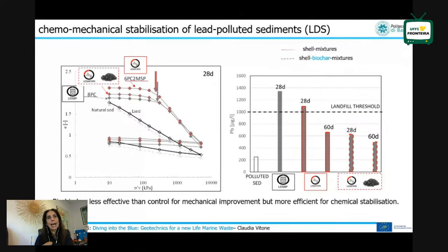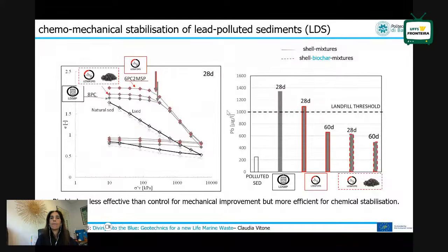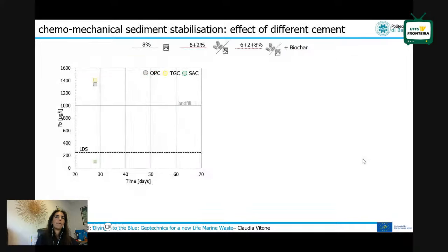On the chemical side, the leaching tests are very interesting here, because you can see that compared after 28 days with the control mixture, so cement and sediment, the new mixtures, if we implement the shell powder, are entrapping the lead in some way. So after 60 days, we are below the landfill threshold, and when we add biochar, of course, the solution is working even better.